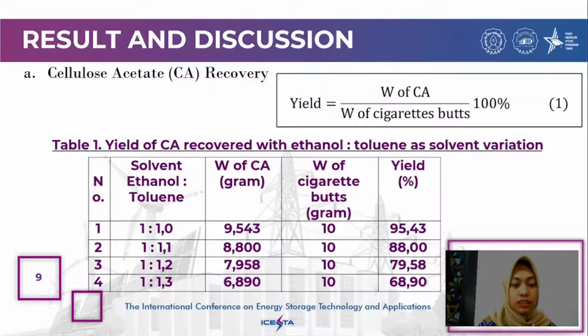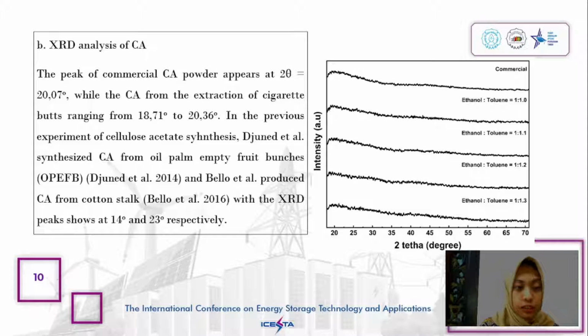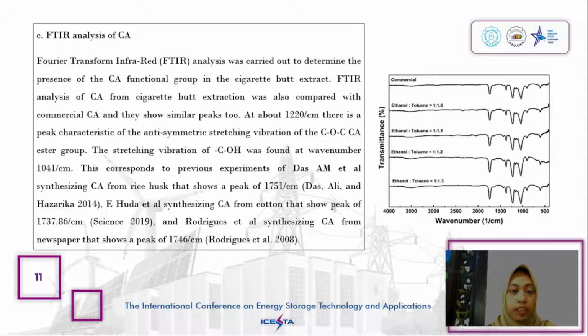The first result is the yield of CA recovered with ethanol and toluene as solvent variation. We obtained the highest yield at 95.43% in the first variation, where the ratio of solvent ethanol to toluene is 1 to 1.0. This is the result of XRD analysis of cellulose acetate. We compare the cellulose acetate from cigarette butts with commercial cellulose acetate powder by XRD analysis, and they show similar peaks. Then the FTIR analysis of CA from cigarette butt extraction was also compared with commercial CA, and they show similar peaks too.